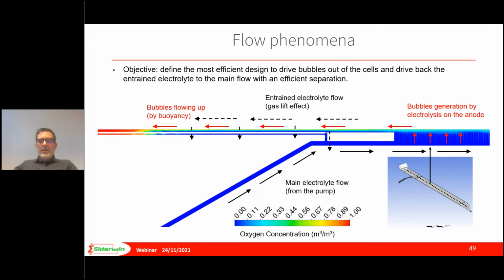And when the current is running through the cell, some iron is going to deposit on the cathode, and some bubbles will be generated on the anode. And because of buoyancy effect, because of gravity, the bubbles will flow up out of the cell. And while they are flowing up to the outlet of the cell, some electrolyte will be entrained by the bubbles. So here in this area, we have a mixing of bubbles and electrolyte that we need to separate in this area so that we can send the bubbles out of the domain and get back the electrolyte and send it back to the main flow. So this is a kind of loop for the electrolyte that allows an efficient electrolysis of the electrolyte.